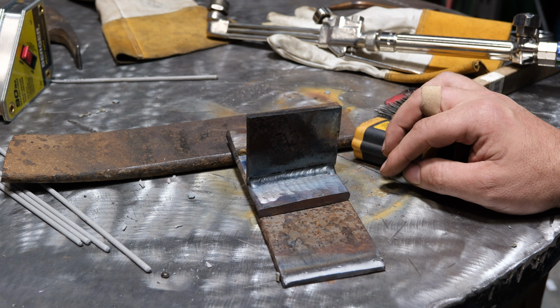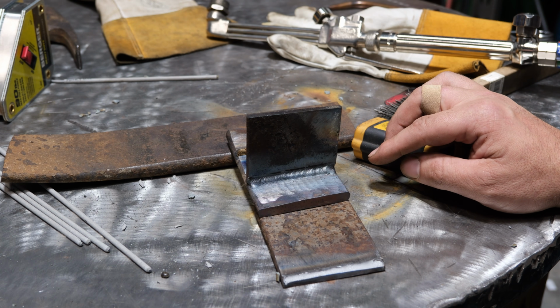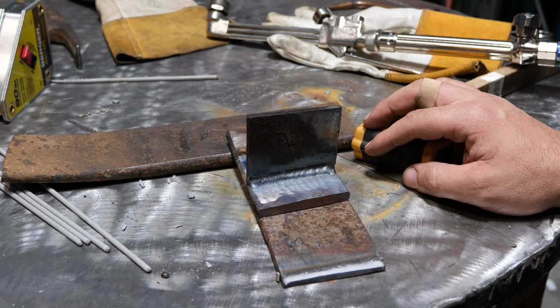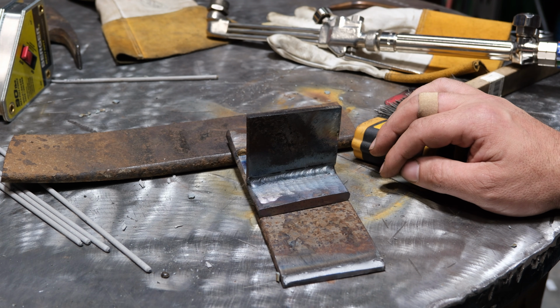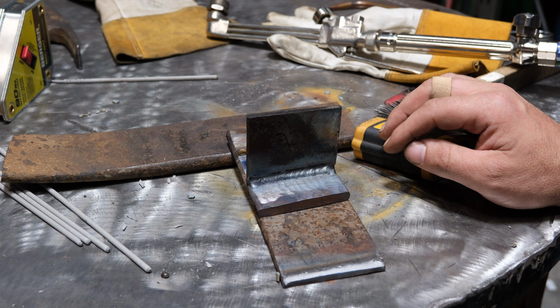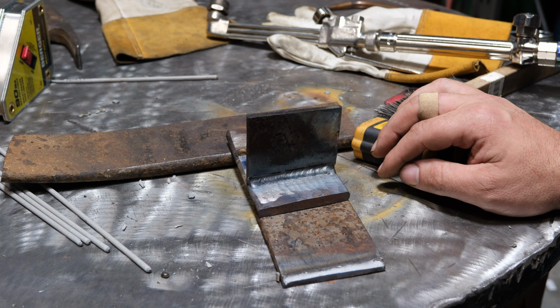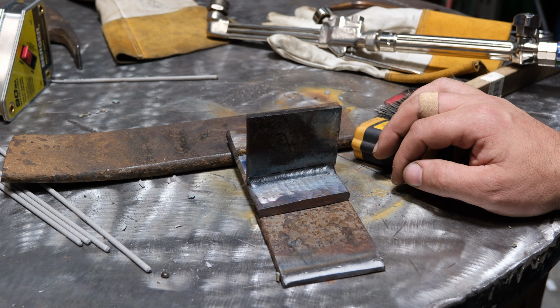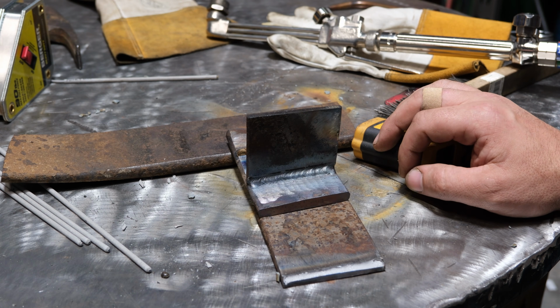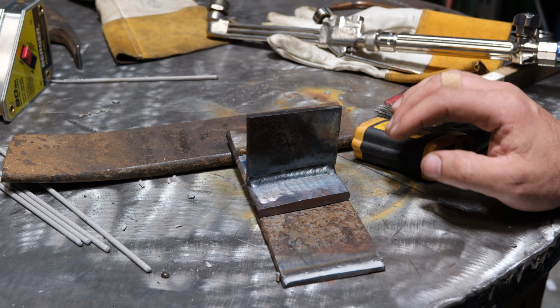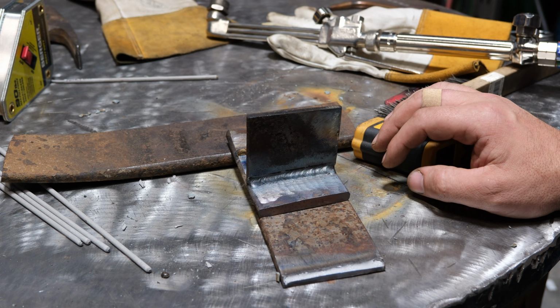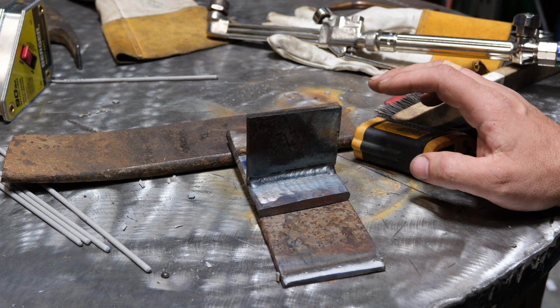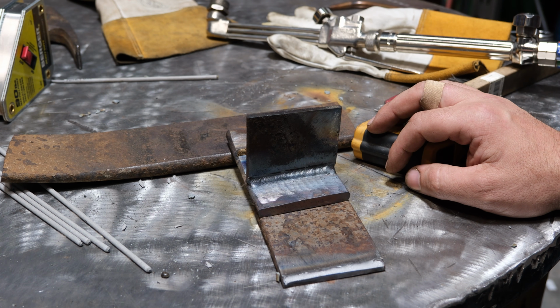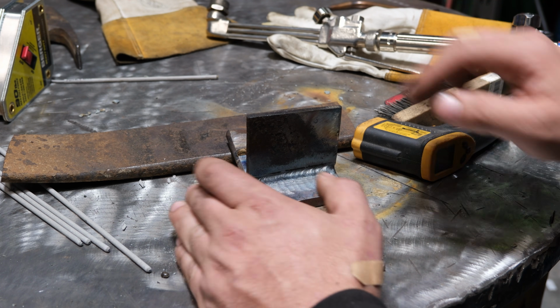Going back to what I was saying about the low hydrogen, 312 stainless and many of those wonder rods that are out there oftentimes are not properly stored. Generally speaking, 312 and most stainless rods should be stored in a rod oven or taken out of a brand new sealed pack. So even with those rods, you should be smart about it and keep a sealed pack around and use them for repair like this on an as-needed basis. And once again, do not use them if they've been out sitting, absorbing moisture for a while, because again, it can lead to hydrogen embrittlement.